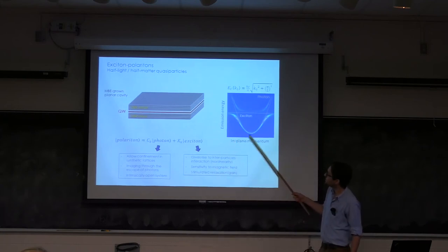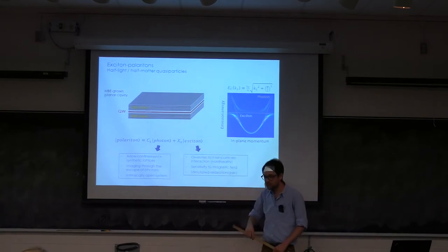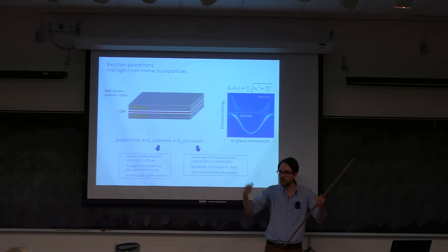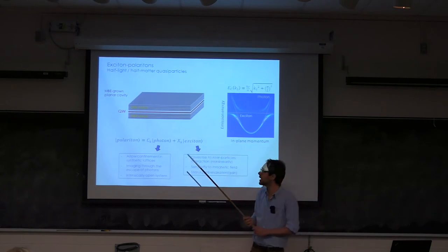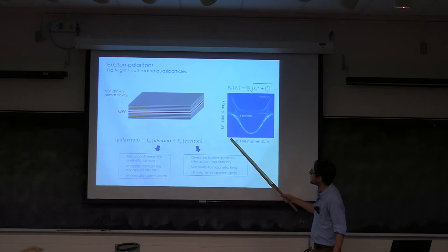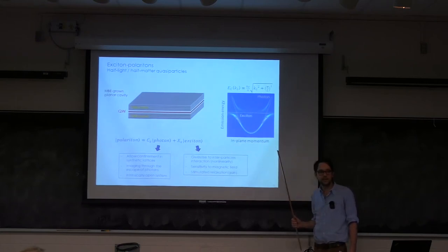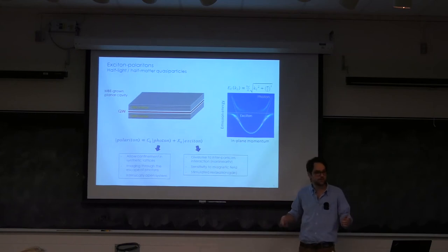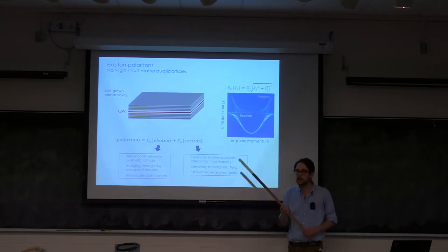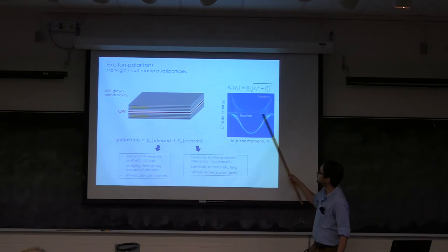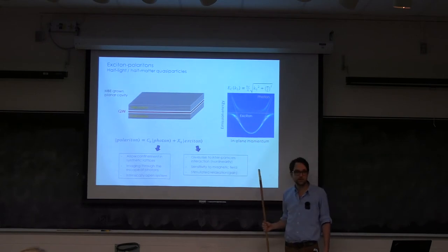So I'm showing here an example where we have this cavity. We shine a laser off-resonant. It creates a bunch of carriers. They thermalize and they populate the lowest energy bands, our polariton bands. Eventually, photons will leak outside of the cavity, and we measure them as a function of their energy and as a function of the angle at which they came out of the cavity, which we can relate to their in-plane momentum. So this is a single-shot image. It's a 10-millisecond image that we take on a CCD camera, and you see that we can reconstruct all the band structure of this cavity here. And you see the really nice anti-crossing here between our two polaritonic branches, which shows that we are indeed in the strong coupling regime.